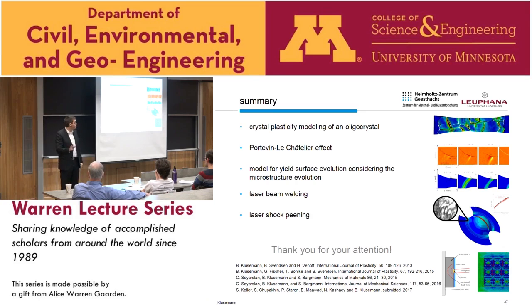For 12, either if we take the 110 or the 112, there were differences, clearly, but both were also quite accurately describing that. One assumption I have to say, which we took here, is that the 110 and the 112 direction glide systems are equivalent. So we took the same parameters. In the literature, sometimes they say there is a 5% difference. We didn't account for that, to say that clearly.